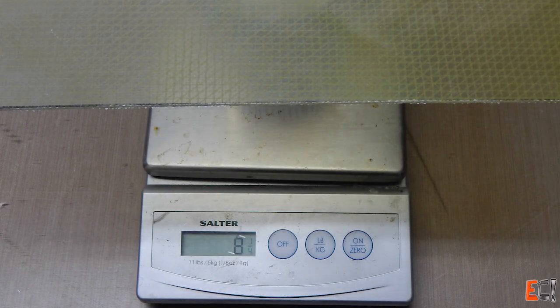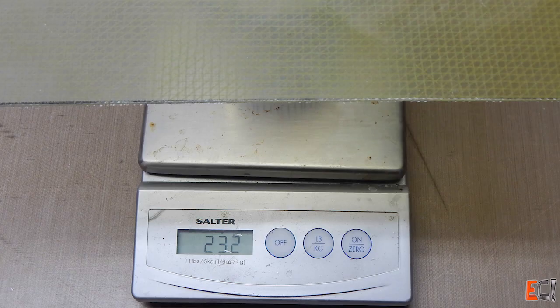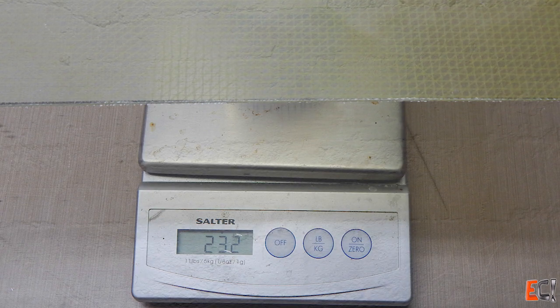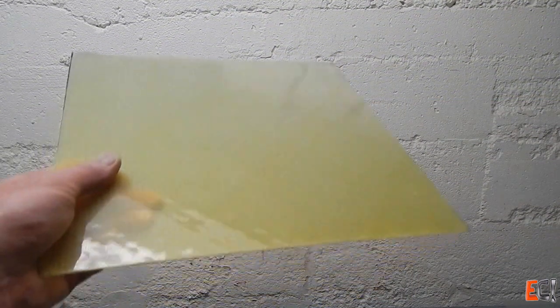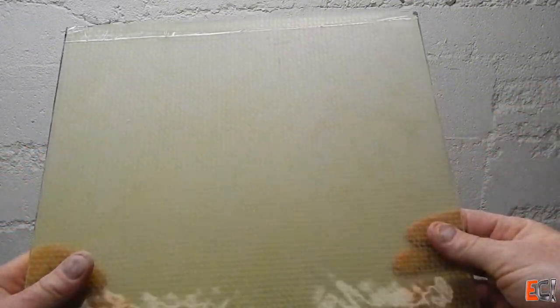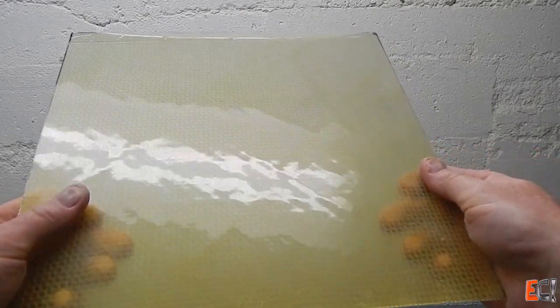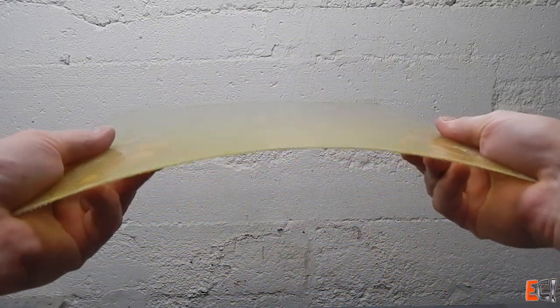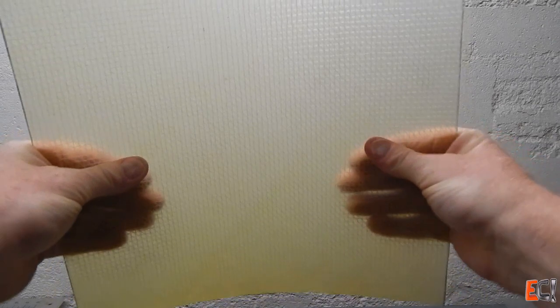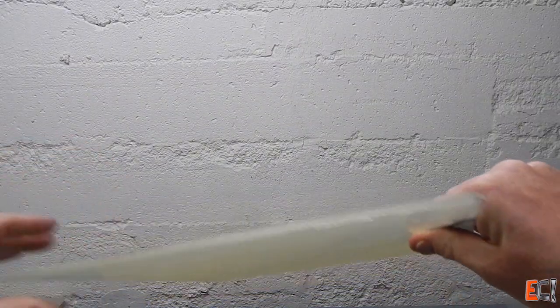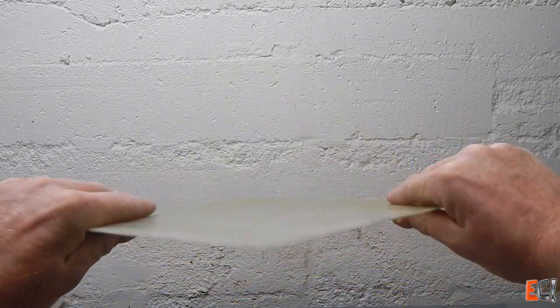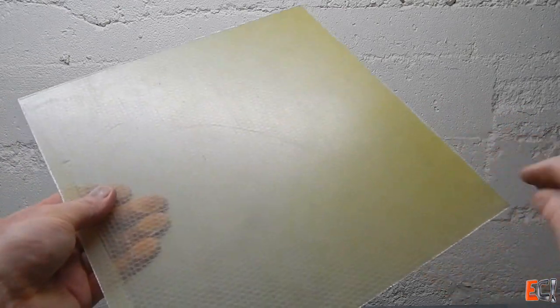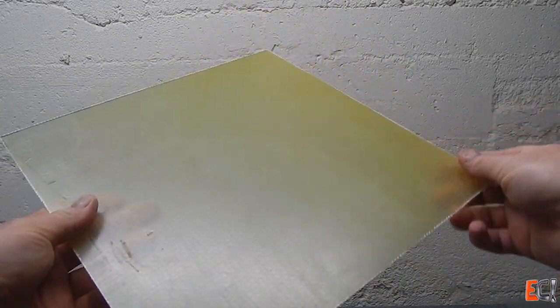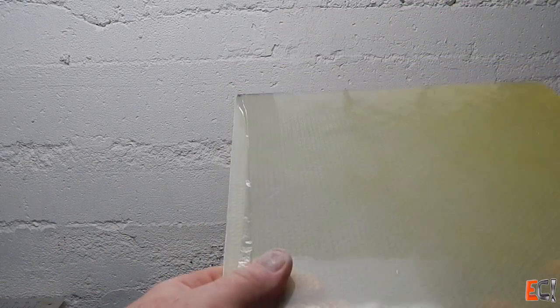All up, the panel, once I trimmed it, weighed 8.25 ounces per square foot, 232 grams. It's relatively low resin content, and I ended up a little lighter than I had predicted. Didn't quite make 1 foot, 300 millimeters, under the caul plate, but very close. So there's a little bit on the edge there with peel ply that I had to leave on to get my square foot. But you can definitely see the color gradient here, and